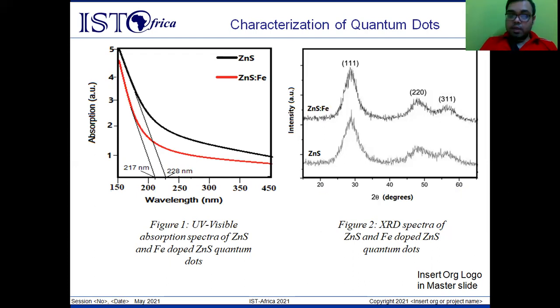And in figure 2, we can see the XRD, that is X-ray diffraction spectra. You can see there is no observable change in the doped as well as in the undoped quantum dot. This is actually what we desired. We didn't want to cause any kind of change in the crystal on doping. So by obtaining a similar pattern of XRD, we can conclude that no changes have occurred in the crystal due to doping. This is what we desire.